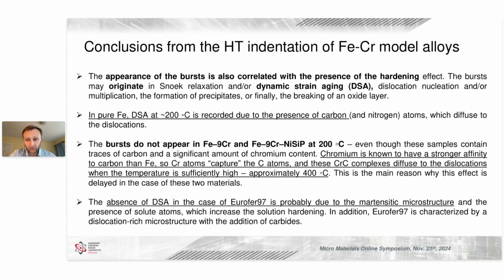So we did some reading, especially we checked some simulations of those systems, and we checked the chemical composition of all the materials, and we saw that in the case of iron, there is carbon in the system. The carbon amount is at a ppm level. However, this is enough for carbon to migrate and diffuse at certain temperatures. And this is what is happening at 200 degrees, because 200 is enough for carbon to diffuse and lock dislocations, which are generated due to deformation. So these bursts observed at 200 degrees for iron basically mean that carbon is blocking movement of the dislocations.